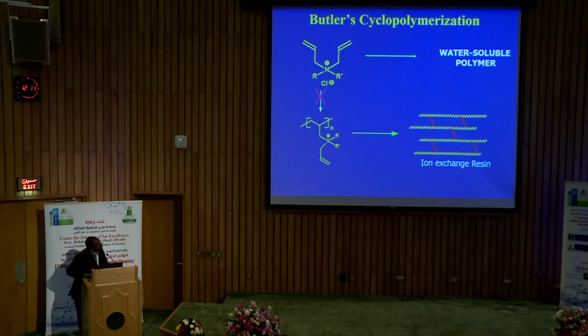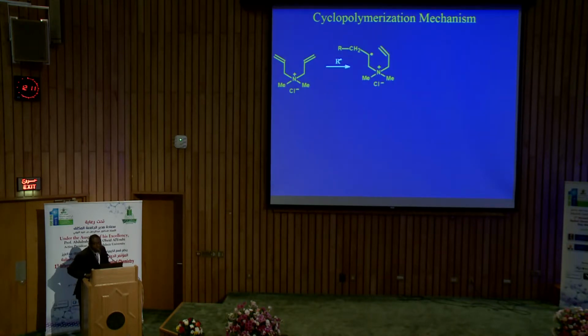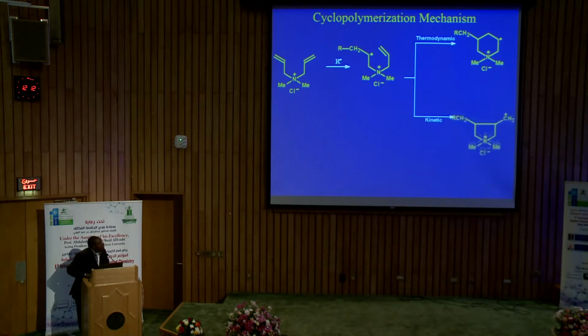To explain this observation, the monomer undergoes free radical addition polymerization, in which the free radical attacks one of the double bonds to form a secondary free radical. It was initially thought that the next step is intramolecular cyclization to form a six-membered ring, which is the most thermodynamically stable free radical. But subsequent studies discovered that it goes through a kinetic intermediate, which is a primary free radical. Since that time, a lot of polymers in this area were produced, and this is one of them.